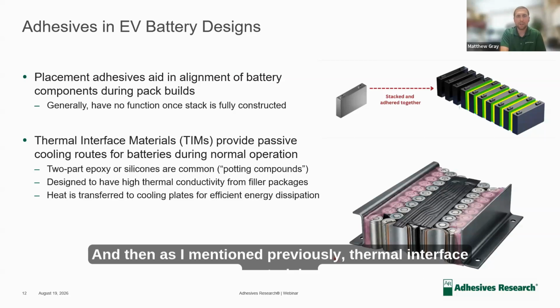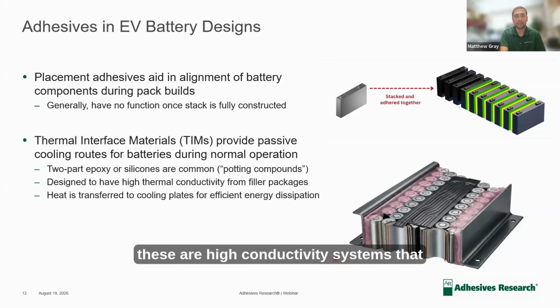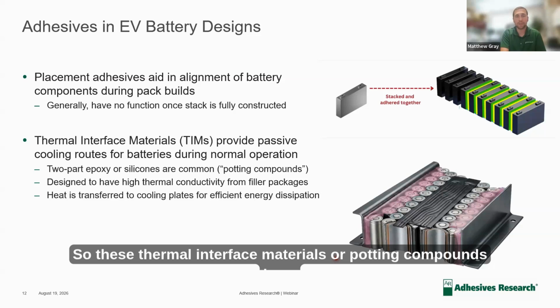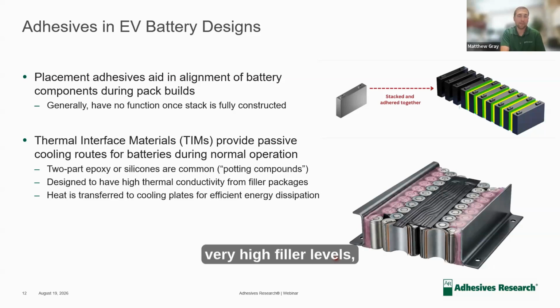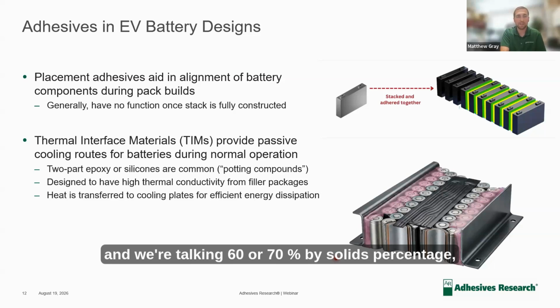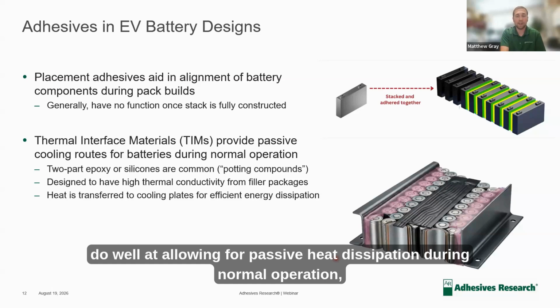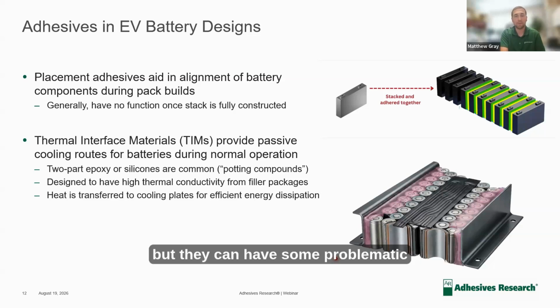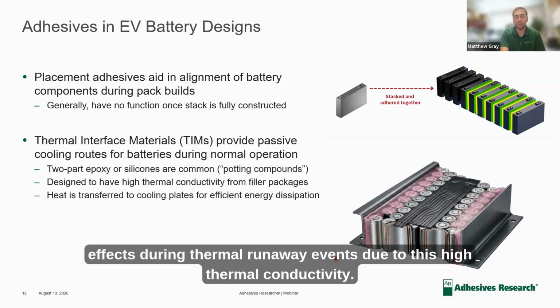And then, as I mentioned previously, thermal interface materials. These are high conductivity systems that are placed between the battery cells themselves that allow for wicking of heat during normal operation. So these thermal interface materials or potting compounds have very high filler levels. We're talking 60 or 70% by solids percentage, which allows for what's called a percolation network, or easy transmission of heat between the two surfaces due to the high level of fillers that are in these potting compounds. And so these thermal interface materials really do well at allowing for passive heat dissipation during normal operation, but they can have some problematic effects during thermal runaway events due to this high thermal conductivity.